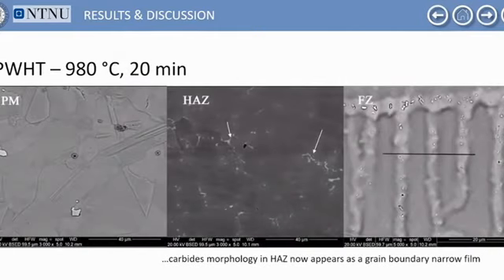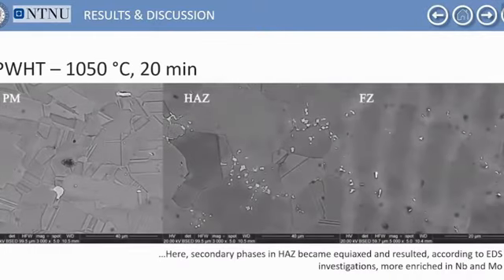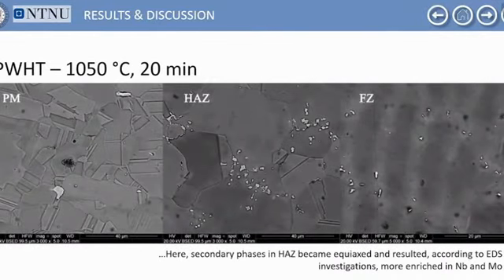Moving to the microstructure of the post-welded heat-treated joint at 980 degrees, we observe more or less the same microstructure of this welded joint with a variation in the morphology of the carbides that now appear as grain boundary film, as you can see in the heat affected zone micrograph. Moving to the microstructure of the post-welded heat-treated joint at 1050 degrees, we observe, of course, the same microstructure as in the previous case, but now the carbides return to be equiaxed in shape.